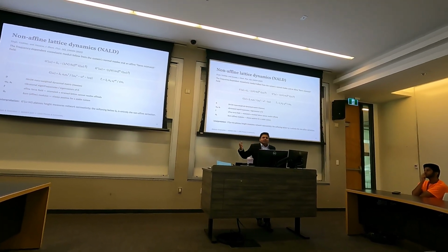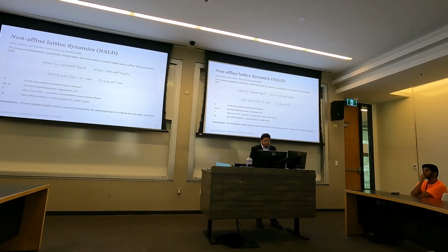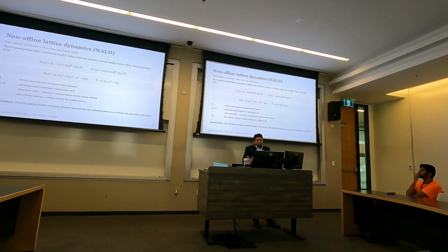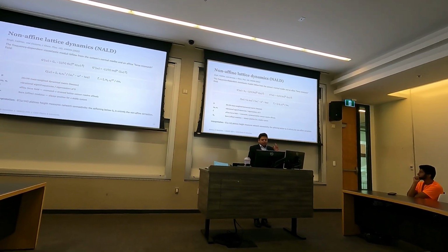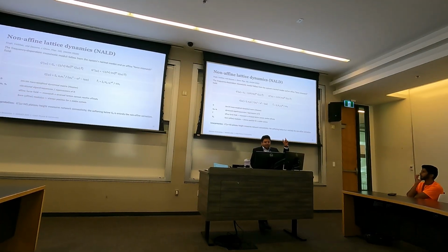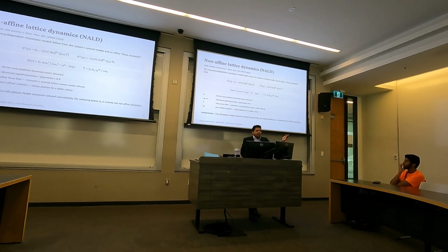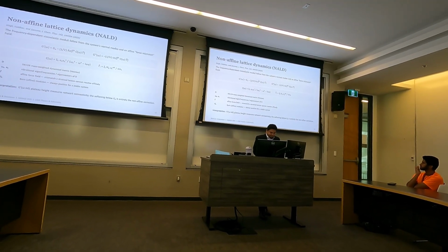Basically, the extra force that is being applied on each atom at this point. And G_A modulus is nothing but the purely affine force modulus that we see, like in a crystal. So the correction of gamma tilde is being added into the G_A in order to eliminate the affineness in the non-affine motion in this case.